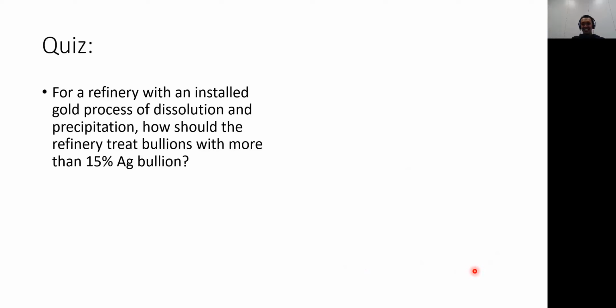So bear in mind, we are using aqua regia to dissolve this bullion. Aqua regia, as we know, has nitric acid content and also hydrochloric acid content. Silver cannot be dissolved because of the chloride ions, so silver will form silver chlorides. So this material, with 15% of silver, is hard to dissolve.